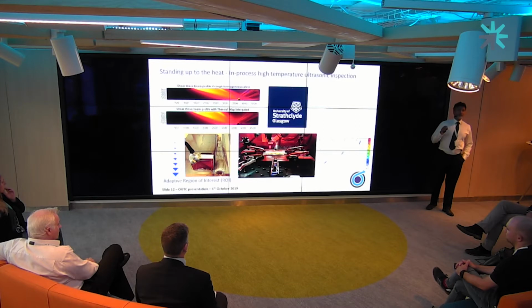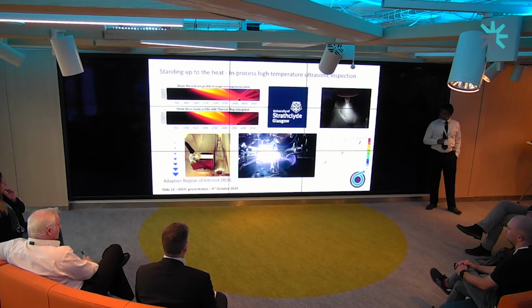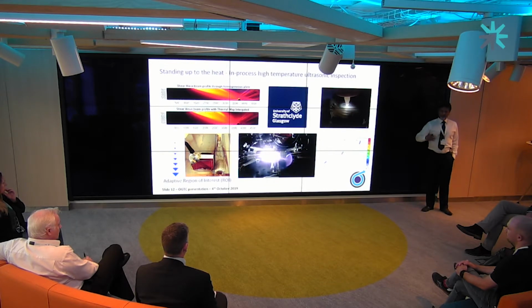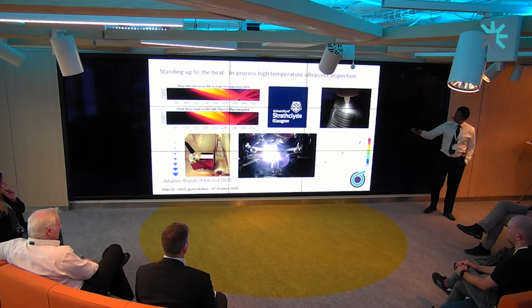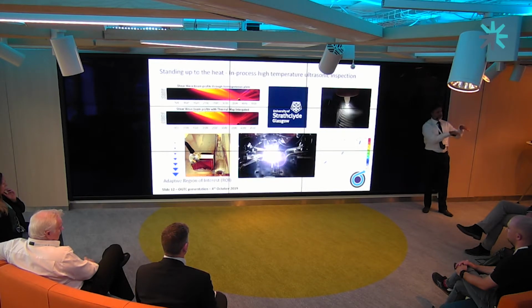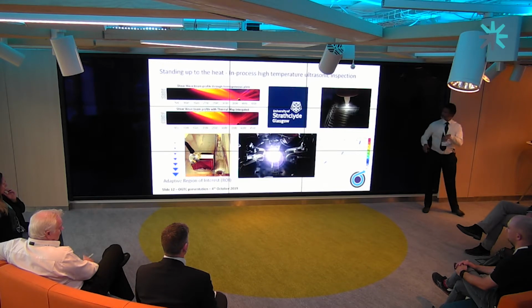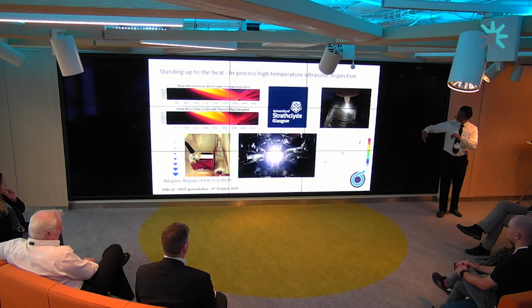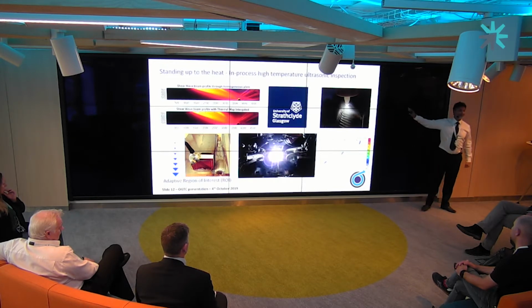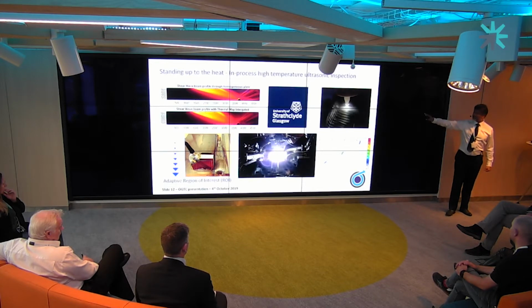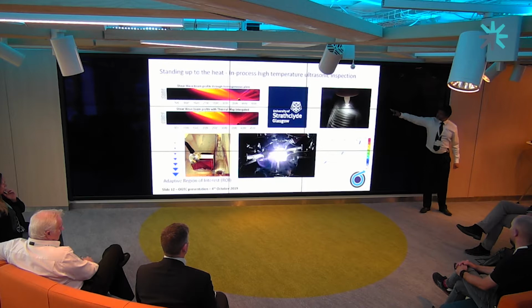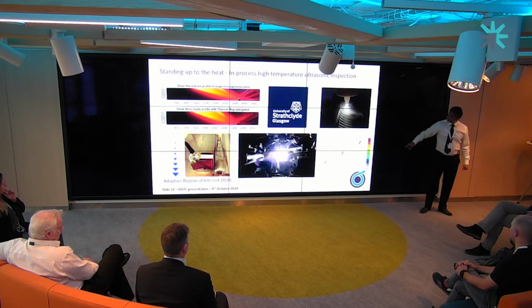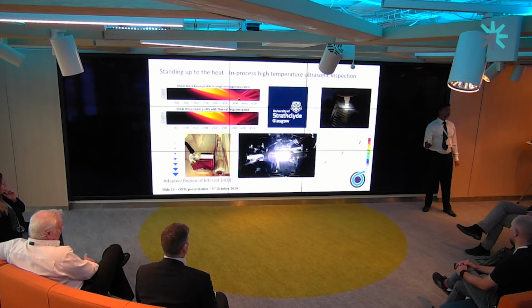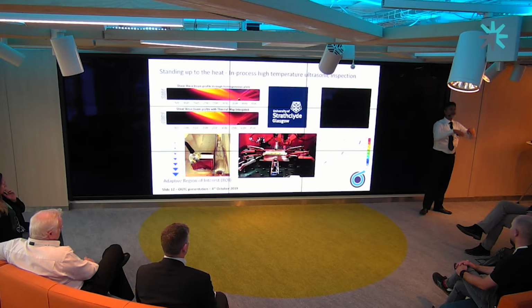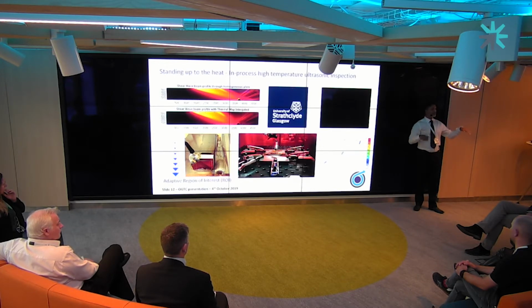We've also got some great work being done by our colleagues at Strathclyde. What you're seeing here is, we know we've got to move in stages, but ultimately it would be good if we could understand, as the temperature goes up and we reduce that cycle time, how we can use high temperature ultrasonics. So what you've got here is a robot doing an oscillation, and apologies, by the way, I forgot, if anybody's suffering from epileptic response, it can be quite a nasty thing. But what you're seeing here is real time. So the weld is being created. When that's done, there's a time period in which you get up to 150 degrees, and then we look at coming in with ultrasonics to see how the defects are forming. So it's quick to actually try and halt any problem that may occur downstream.